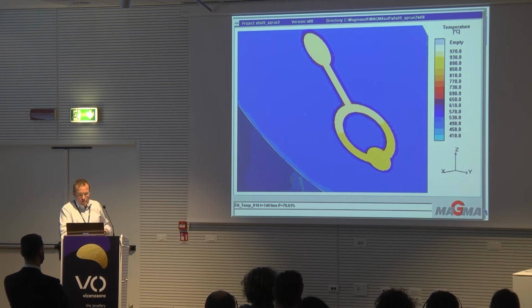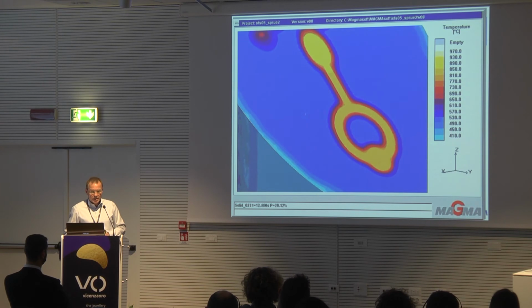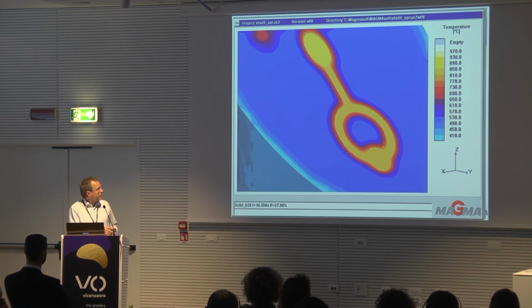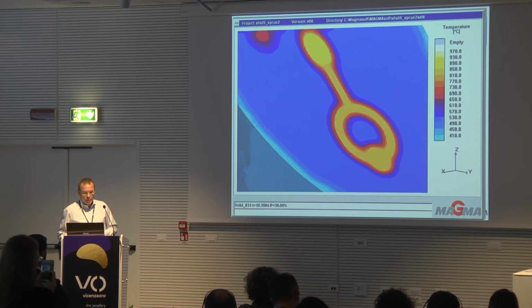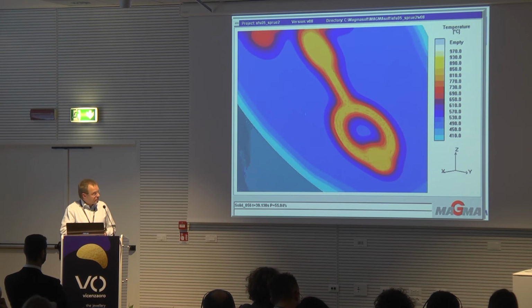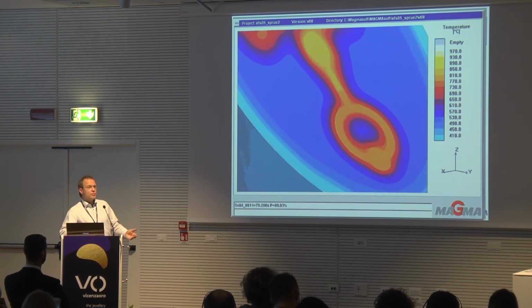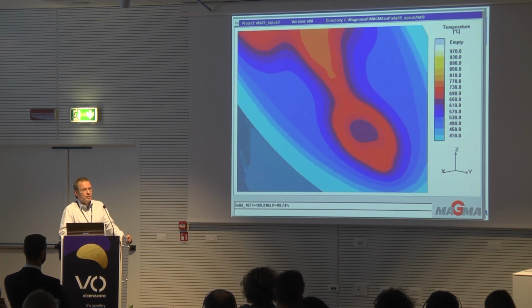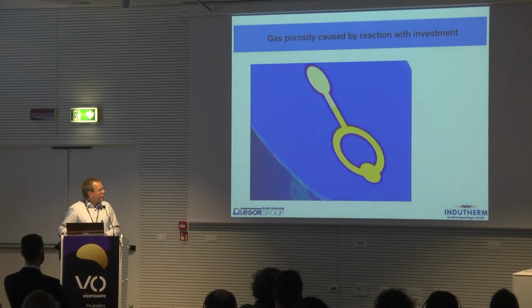And what you can observe now, if I let the video run, you can see temperature increasing a lot in the surrounding of the as-cast part, especially in some areas where heat dissipation is restricted. The flask, the investment material can become very high in temperature in the direct surrounding of the casting. And the investment material is only stable up to a certain temperature. It will also depend on the metal properties, whether the metal is reactive with the investment or not.